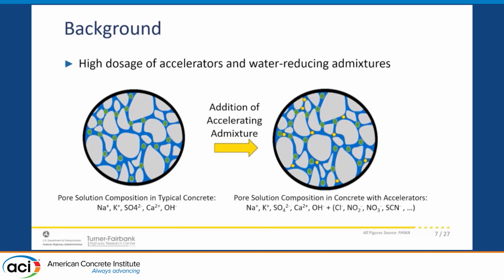What happens, though, is that once we started looking into the specifications of many DOTs, there's barely any quality control done on these mixtures. We care about the strength, but we don't really care about anything else that happens to that mixture itself. Some reports have highlighted that because of the lack of interest in any other property, we see fairly early, premature failures in a lot of these sections that are being repaired. So we repair them, and then within a few years they fail again, and so we have to repair them again. So we started looking into how we can improve the way we test these mixtures.